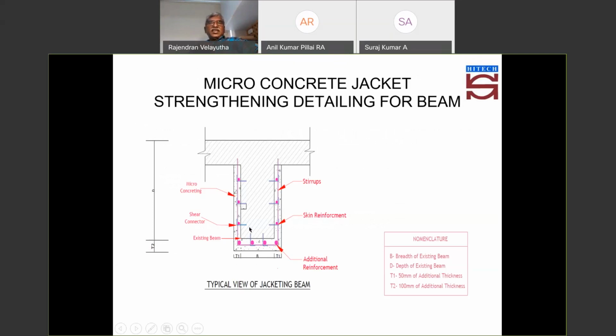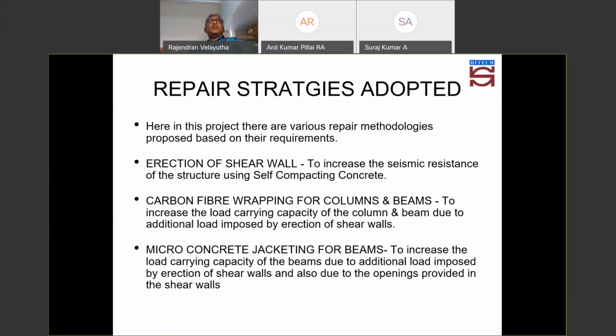As far as the shear key depth is concerned, you can calculate the maximum bending moment of the beam and divide by the lever arm, then you get the force. You predetermine the spacing of your shear connectors, divide by the number of shear connectors, and then you get the force coming in a single shear connector. Based on the bond strength, you can decide the depth of the shear key, because that's going to be more important. Otherwise, the micro concrete and the parent concrete will not act as a single element; they will act differently. So this has been followed.